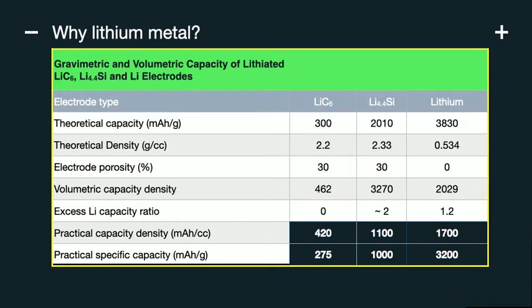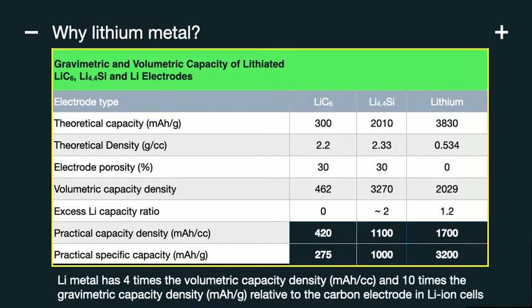Actually, in this very simple table, particularly focusing on the bottom part of the table, you'll see that the energy density or the capacity density of batteries based on lithium relative to, say, carbon are much higher energy density systems. So lithium is four times the volumetric capacity density and 10 times the gravimetric capacity density relative to carbon. So this allows you then to boost the performance of the battery if you make this shift.